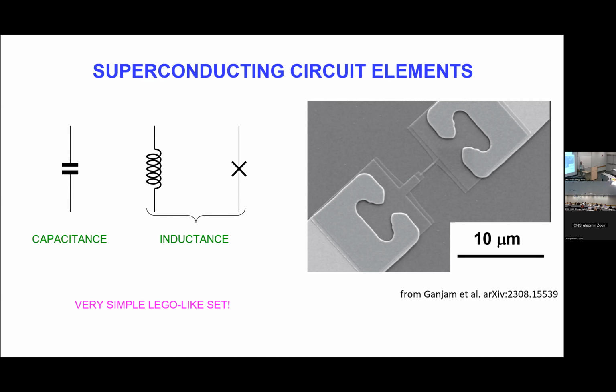Could you point out the actual Josephson junction here, please? Where is it exactly? Yes, let me point it out. The junction is this overlap region here. It's a top aluminum, bottom aluminum with an oxide in between. There's a native oxide, but it's very, very hard to image this oxide on this kind of device. You would have to cut the junction and then do a TEM on the interface.